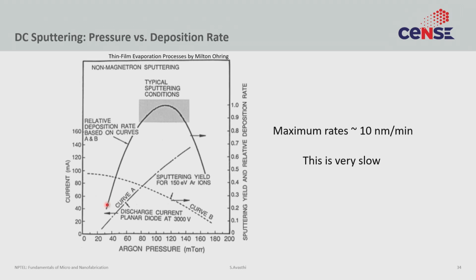At very small argon pressure, you have high sputtering yield, but you don't have enough plasma or enough discharge current. Sorry, you have large discharge current, but you don't have enough sputtering yield. And at very high pressures, you have a lot of sputtering yield, but you don't have any discharge current, which means you don't have any plasma. Optimum lies somewhere in the middle. So for typical simple sputtering, you always have to be in this range of around 80 to 140 millitorr. And the maximum deposition rate you can get is 10 nanometers per minute, which is relatively low.